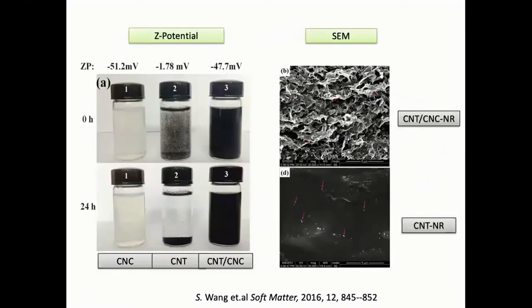This is a very interesting slide for you. See the nanocellulose that we get from nature. This is a dispersion in water. You see how stable they are, at 0 hours and 24 hours. But if you look at the man-made CNT, at 0 hours you get a good dispersion. If you keep CNT for 24 hours, you know what happened? The whole CNT settles down. But if you mix CNT and nanocellulose together, you see it's pretty stable. This is the advantage of hybridizing two nanostructures together, CNT and nanocellulose.